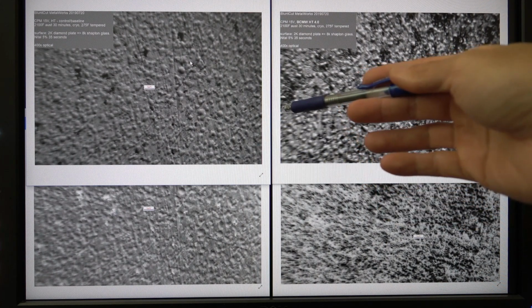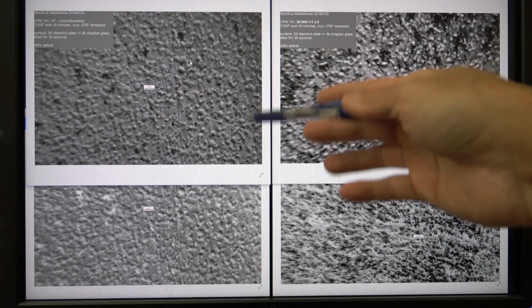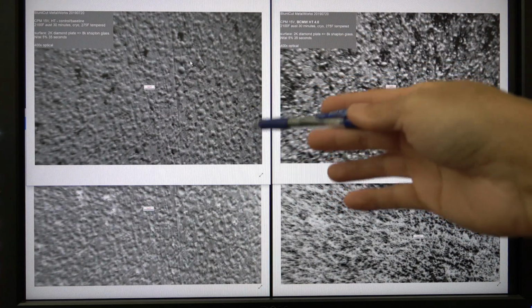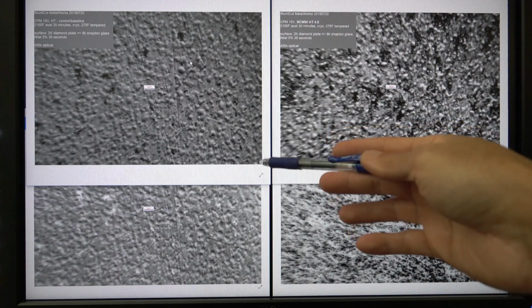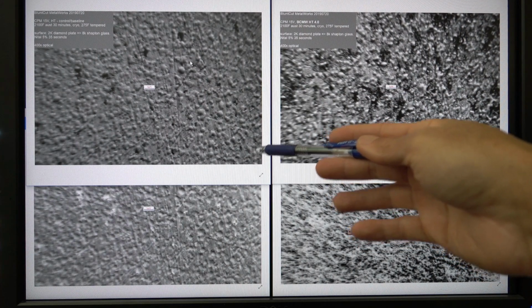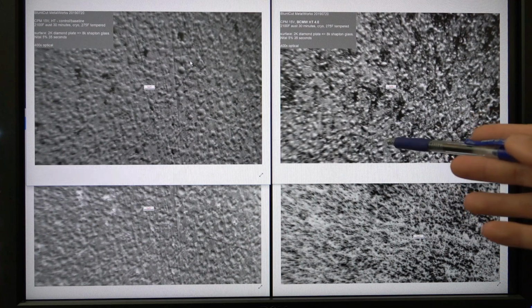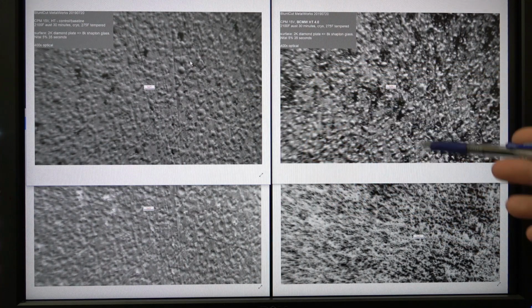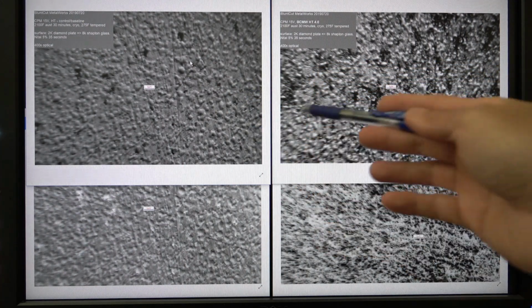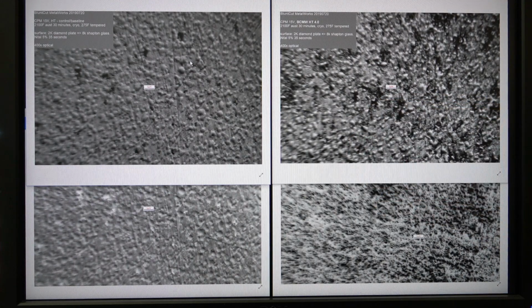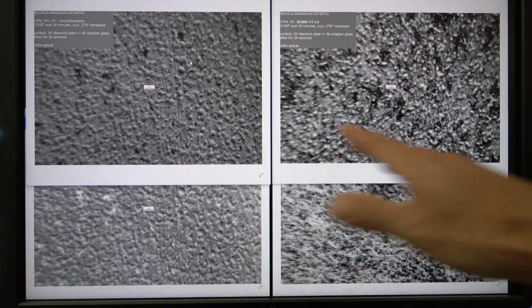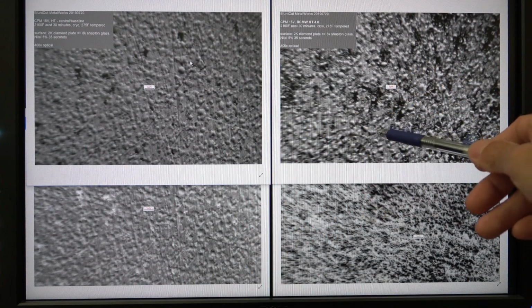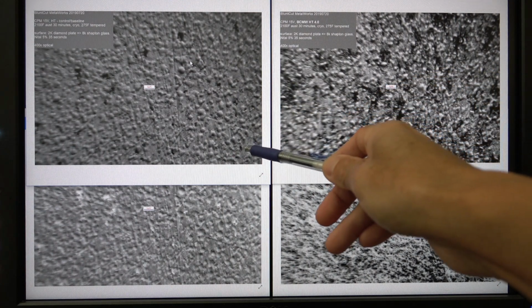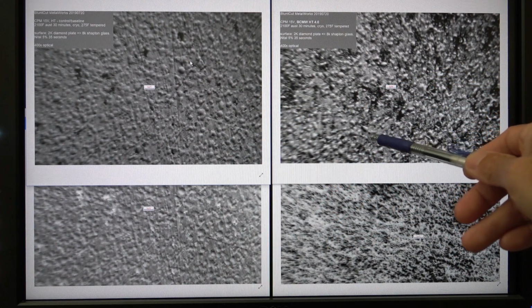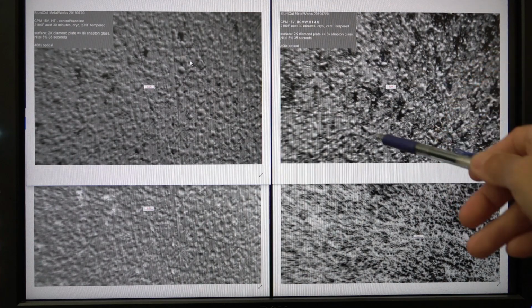So when I have the SEM picture, then it will become clear. These are pretty much the same sample. I consider this sample good enough for SEM, scanning electron microscopy. Then I will do a follow-up video. But from this picture, it's clear enough to qualify that there's a big difference or big improvement between standard heat treat and Blended Metalworks heat treat.